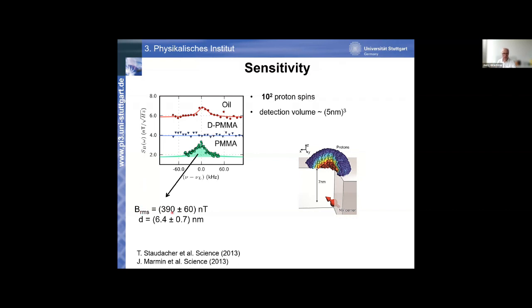The root mean square amplitude of the field is not small, right? It's almost half a microtesla. The distance between the spin here and the spin here is on the order of say 6 to 7 nanometers. And the effective signal comes from roughly 100 proton spins out of a detection volume of (5 nanometer) cubed. So it's a rather sizable signal from a small number of proton spins, which one is able to detect because you can go close to the source of the signal. So it's a proximity sensor.